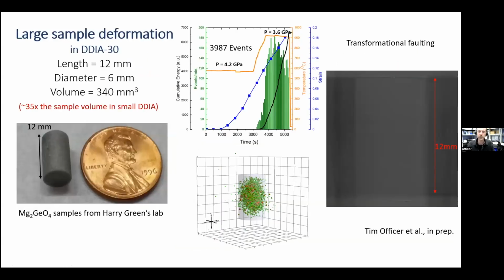And since this is force, I should mention that we also have run these experiments with big samples. Big samples are the key for this. You can generate larger fractures. You generate much more events. Here we got about 3 times as many, but we didn't strain it as much as we did in the previous examples. And also our transducers are much further away in this case because we have a double stage anvil system.